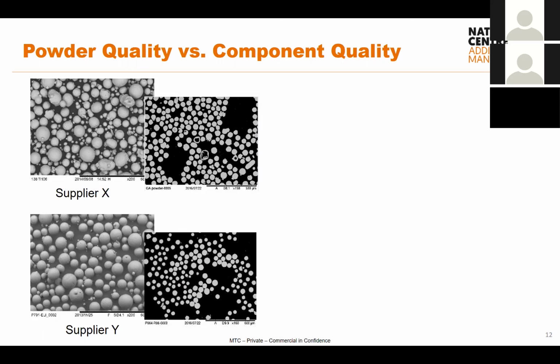But what's really interesting about these two suppliers is supplier X tends to have more instances of particles with pores. So you can see that in the second SEM image at the top. You can see an outline of a grey particle, but then with a black void in the middle. So that is a pore inside a polished particle. Now, there seems to be a complete absence of those porous particles in supplier Y.